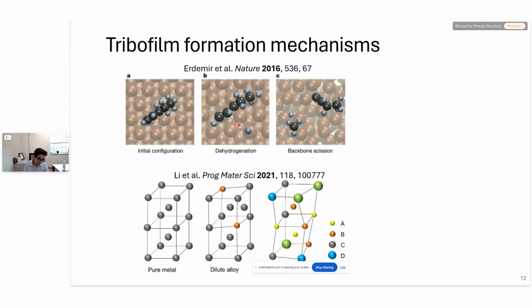Now, this result is also very remarkable because most prior studies on catalytic materials require a lubricated contact to generate tribofilm. It could be an oil molecule like the study shown on top here, where polyalpha olefin is supplied to generate carbon-based tribofilm. Or it could be vapor phase lubricant, where the organic vapors are introduced in the chamber and those molecules react and form tribofilm. Unlike these prior studies, in our system, we can generate these tribofilms in air, in ambient conditions, which is remarkable.